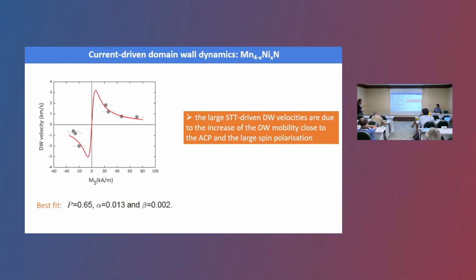So, this large polarization. Our conclusion was that the large spin-transfer torque domain wall velocity can be related to the increase of the domain wall mobility close to the angular compensation point and to the large spin polarization that is given here. And the last thing to say is that according to the model, you have a vanishing magnetization, vanishing velocity at the angular compensation point. This point where in our fit the velocity is cancelling is the angular compensation point.